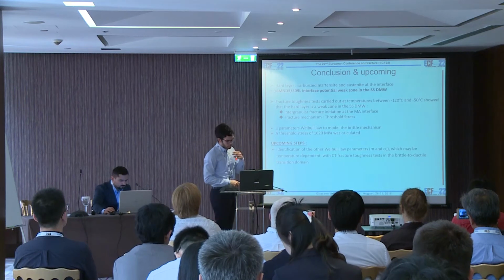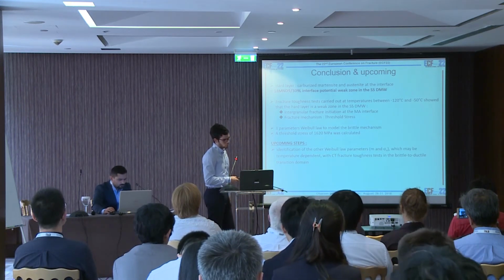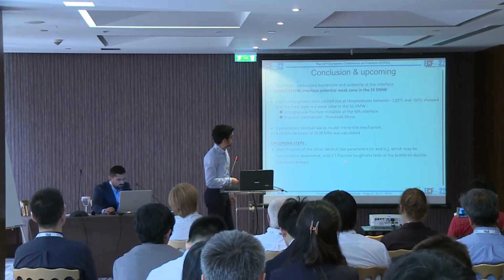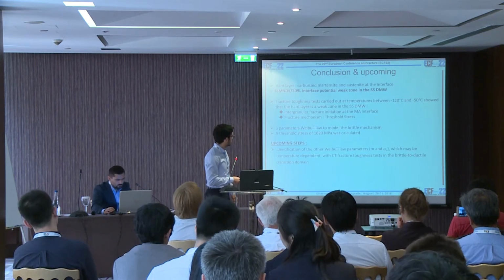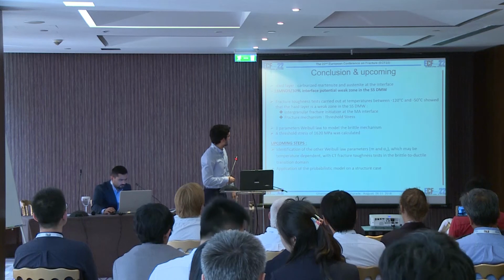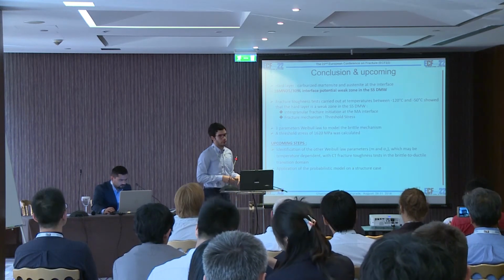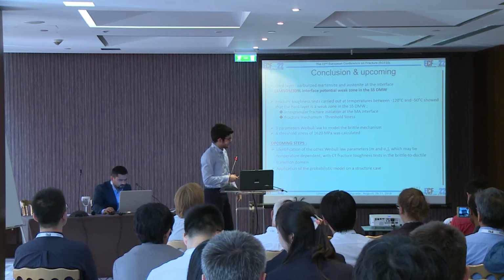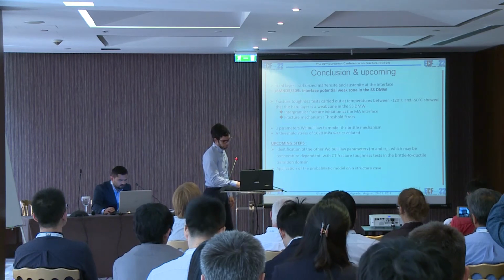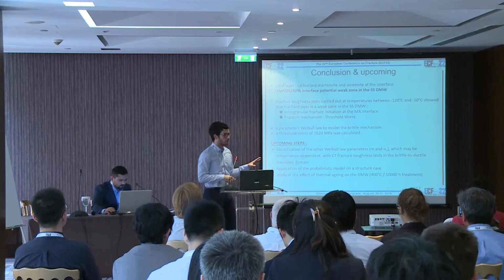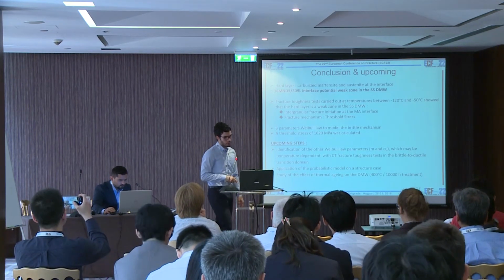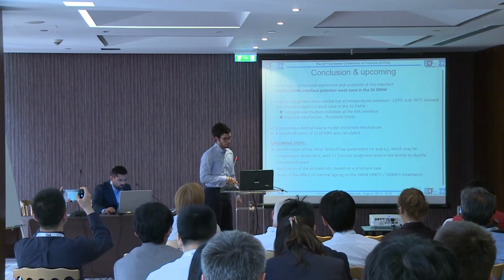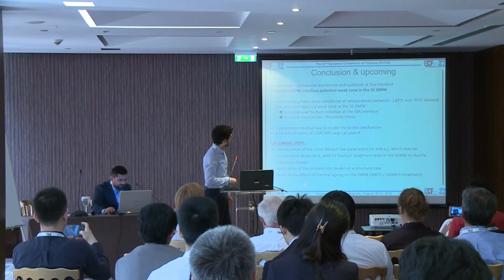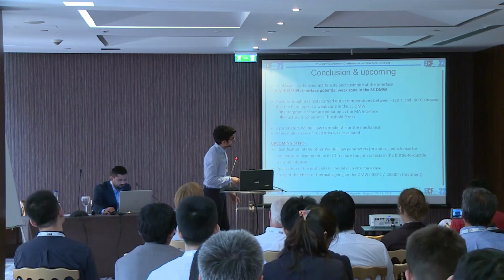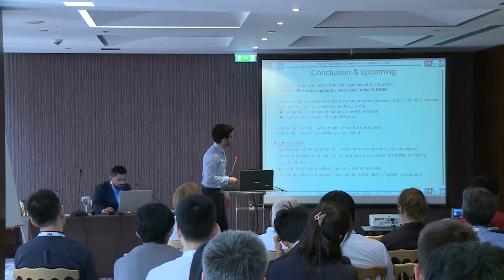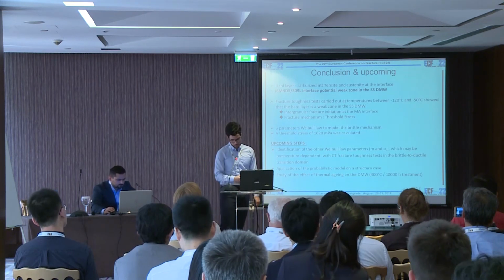And so to complete this work, we have to identify, of course, the other Weibull law parameters, which may be temperature dependent, so have to be identified with CT fracture tests in the brittle to ductile transition domain. And so, of course, we have to apply this probabilistic model to other geometries, so SENT specimens, and eventually to a real structure case. And last point is that, as I said in the introduction, we have to study the effect of thermal aging, since we want to extend the lifespan of these facilities. So we have to study the effect of thermal aging on the DMW by some heat treatments we do, and we study the effect on toughness and on mechanical properties.